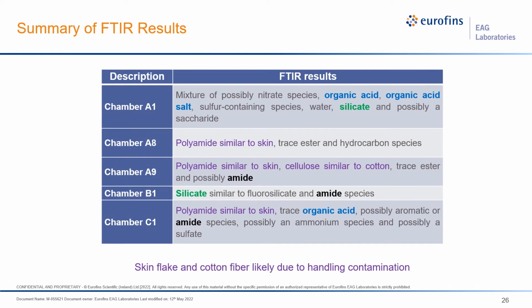Chamber A, we saw organic acid, maybe sulfur species, maybe nitrate, saccharide, some candy or something. Chamber A8 and A9 from the same lab, just a different chamber, were quite clean. B1, at least by FTIR standards, was fairly clean. Silicate, we often see that, and these are subject to damp heat, so there could be some small transformation to the wafer, but we do see some amides in a lot of these, and those could potentially be problematic.